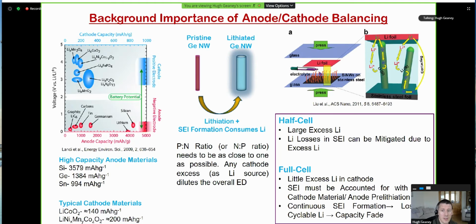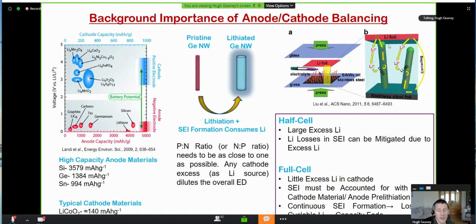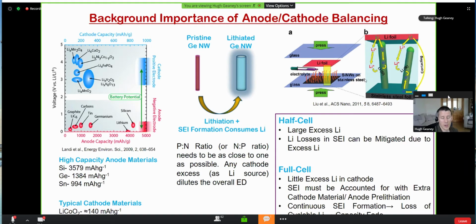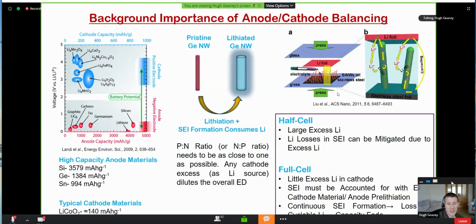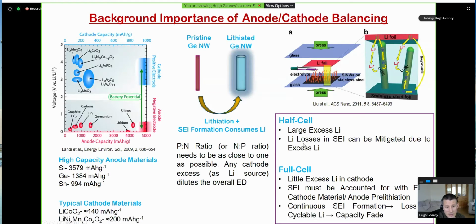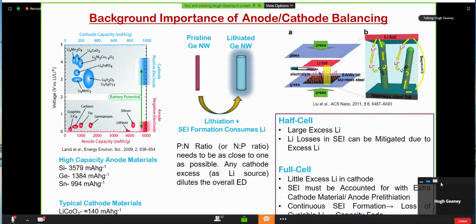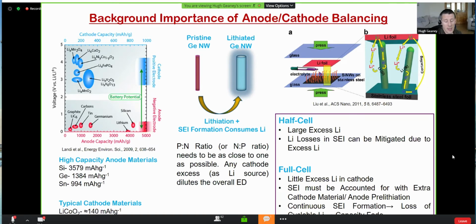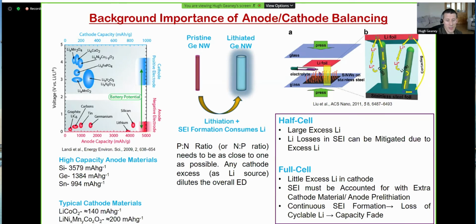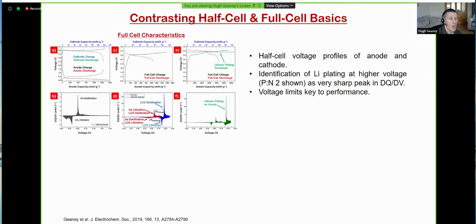So there's a couple of ways of doing this. There's contact methods where you can pre-lithiate the material to try and get around those irreversibility issues. And there's also electrochemical methods like the one I'm going to show on the next slide. So in terms of a half cell, again, we have a large excess of lithium due to the fact that we have a lithium counter electrode. And as a result, lithium losses in the SEI can be mitigated due to that excess lithium. Whereas in a full cell, we've little, if any, excess lithium in the cathode. The SEI has to be accounted for with extra cathode material or with an anode pre-lithiation. So if we have continuous SEI formation, then we're going to lose cyclable lithium, and it's going to lead to capacity fade.